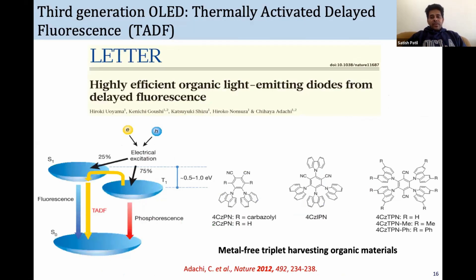So today's LEDs, where my research group at IISc Bangalore is looking at a few aspects, use thermally activated delayed fluorescence. This is a very recent idea from around 2012, where Adachi in Japan came up with the idea of saying, can we make this singlet triplet gap so small? If you understand the exchange energy between S1 and T1 and make it so small, you bring it to room temperature. So the triplet you generate, you collect back at room temperature, purely by using a small molecule. These are metal-free organic molecules where the triplets can be harvested. So you are harvesting those dark states and making an efficient LED out of these materials.